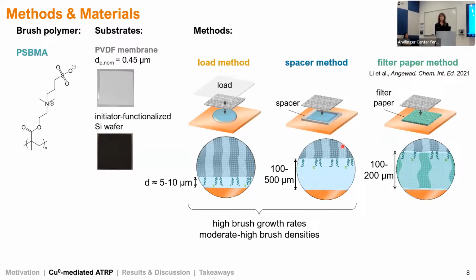So the load and spacer methods, these kind of thin film methods, have been reported to result in high brush growth rates as well as moderate to very high densities. The filter paper method was reported by Li et al. to give higher brush growth rates, although the brush densities reported were slightly lower. So we were interested in comparing these to look at both brush growth and fouling resistance.